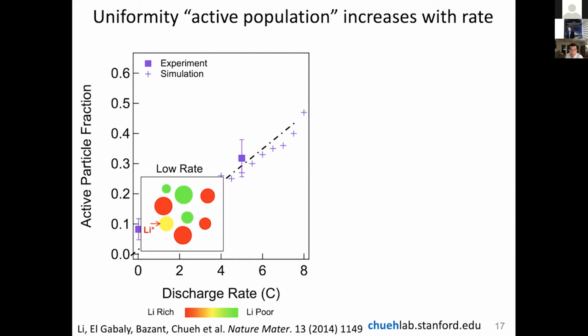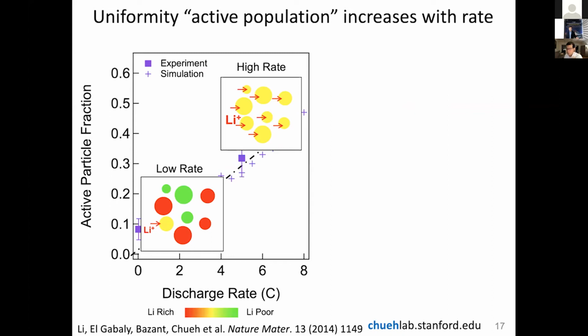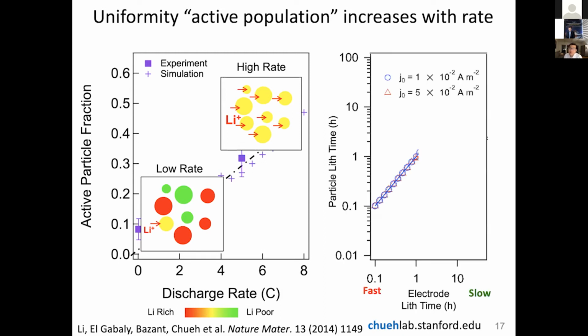So schematically, we have this mosaic effect where very small fraction of the particles intercalate at low rate. But at high rate, you have all of the particles participating. Again, this is very contrary to our standard textbook teaching of kinetics, where the system uniformity actually increases with rate. Let me show you another representation of this.